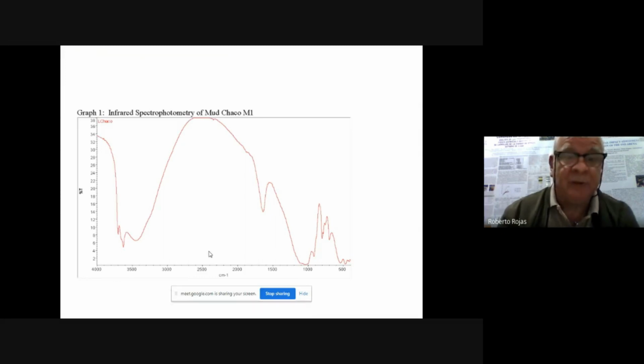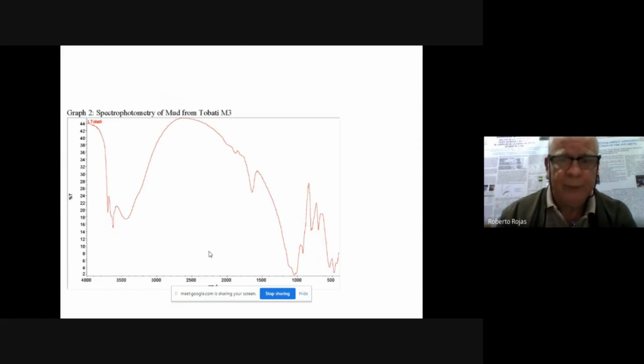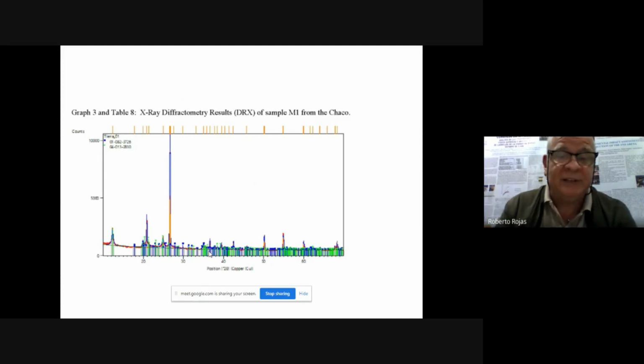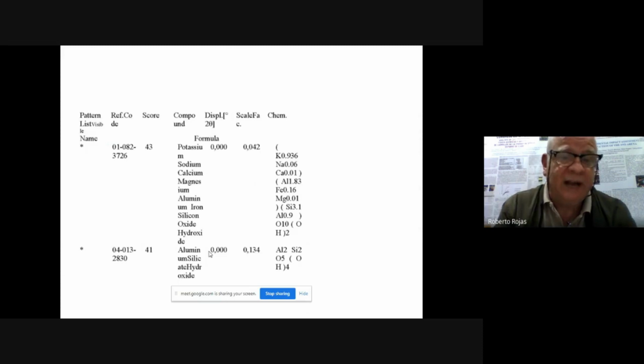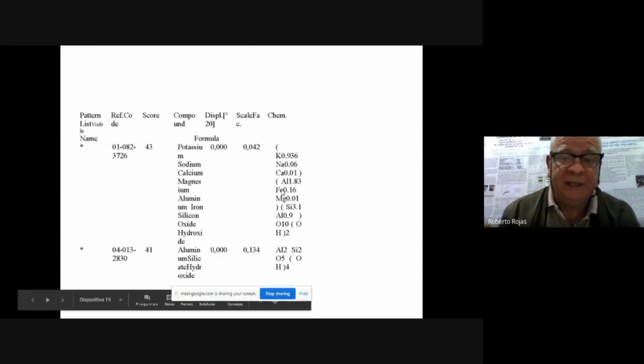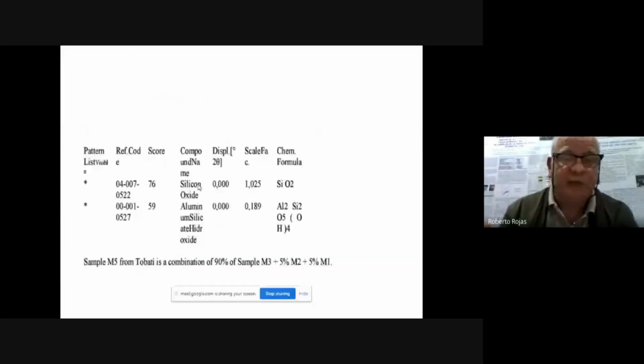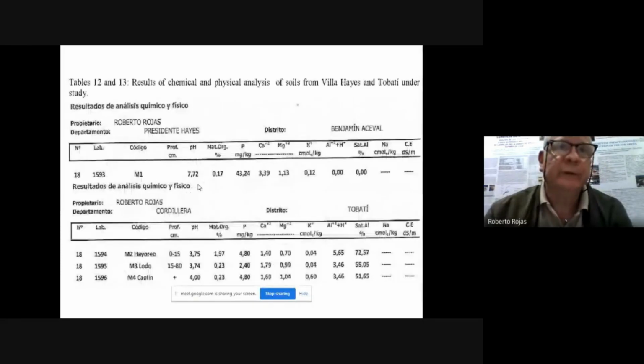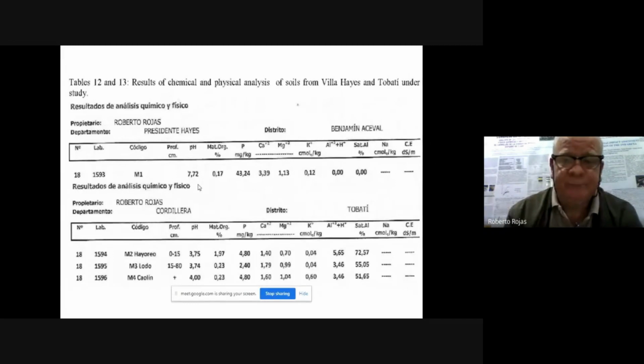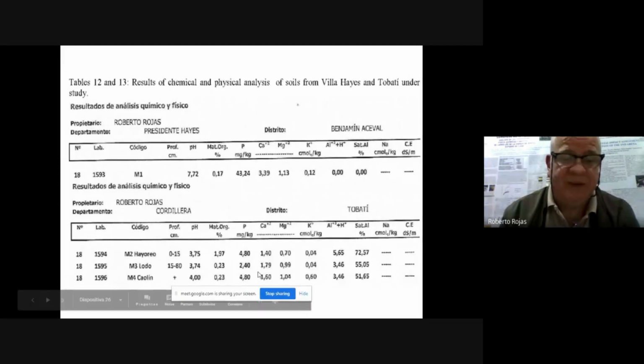This was the infrared spectrophotometry of mud Chaco, M1. This of M3. And here are the X-ray diffractometry results from M1, from the Chaco sample. It was a potassium, sodium, calcium, magnesium, aluminum, iron, silicon oxide, hydroxide. And here is its formula. And the aluminum silicate hydroxide also. M4 also, we have this. And there was a mixture of the others. So we have the results of the chemical analysis from the samples: from the Chaco, Benjamín Aceval, and Tobatí, the three that were mixed to make M5, sample 5.